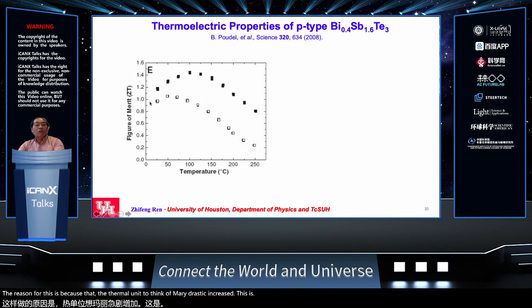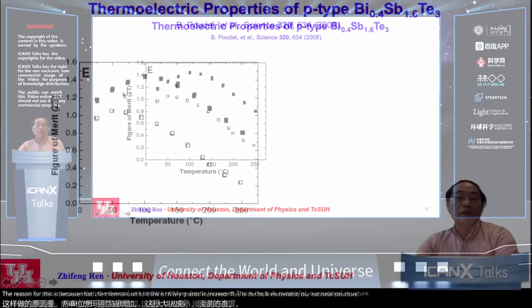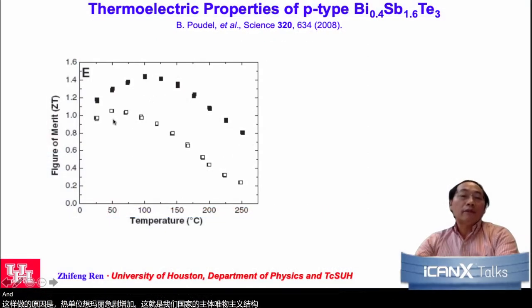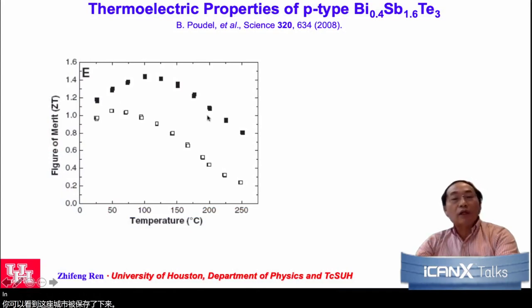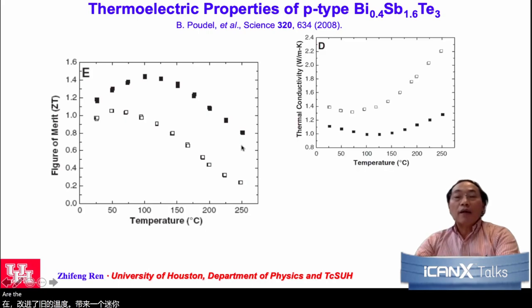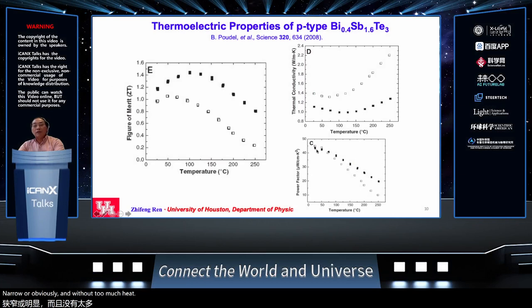This is the bulk material. This is our nanostructure material. And you can see the ZT has been improved over the whole temperature range. Mainly the improvement comes from the thermal conductivity decrease in the nano compared to bulk, obviously, and without too much interference with the power factor.